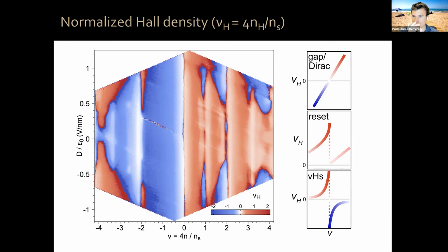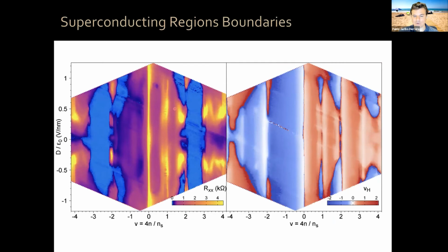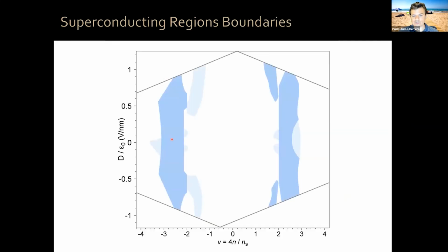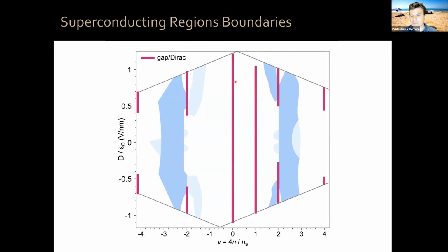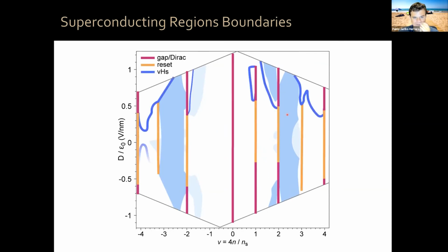So in this diagram, to zeroth order, again, most features can be associated with one of these conditions. So now let's compare these two diagrams, okay? And I'm going to do that schematically. So these are the superconducting regions that we saw before, okay? And now we can look at what the Hall density features are. These regions are where gapped Dirac type of behavior transitions are seen. The orange, we have the reset type of behavior. And in dark blue, we have the Van Hove singularities, okay? And as you can see now, a pattern emerges where superconductivity is mostly bounded by resets at low displacement field, but the boundary is set by Van Hove singularities at large displacement field, okay?